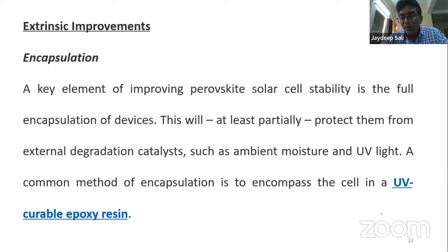Then another way of preventing the degradation is to have encapsulation. It is a very obvious way. You just encapsulate the solar cell with some UV curable epoxy resin, and that will prevent the environmental moisture or oxygen from penetrating into the perovskite layer. So in this way, we can have improvement in its stability.